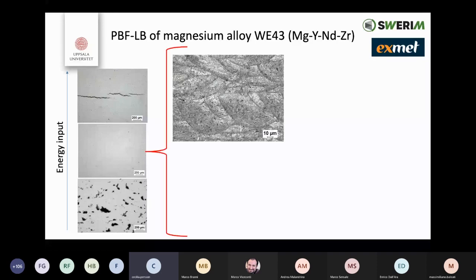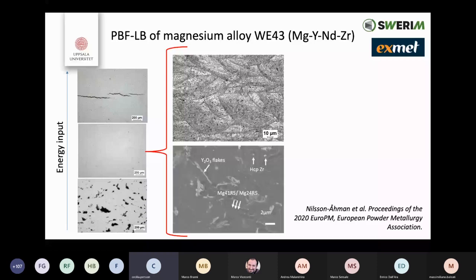If you look at a cross-section of these materials, they look very different to the regular microstructure. You can see the melt pools here, and also you get different types of precipitates, different phases in the material. And this can, of course, have big effects on corrosion properties and mechanical properties of the material.